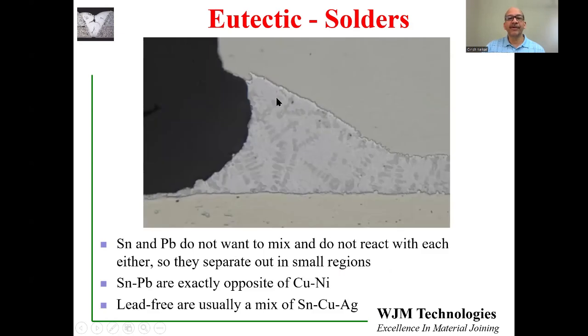Here's an example of a cross-section of a solder connection. And you will see in this solder, this is a solder alloy over here, and you can see dark and light gray regions of lead and tin, which have separated out. They are not reacting, but they don't want to mix either. So it's very unusual. This is exactly opposite of a copper-nickel mixture.